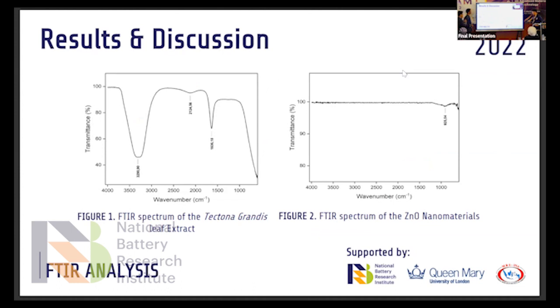Next, result and discussion. Figure 1 shows the FTIR spectrum of Tectona grandis leaf extract. An OH bond in the leaf extract acts as a reducing agent, and formation and stabilization of the nanomaterials was confirmed at peaks at 3290 per centimeter. Figure 2 shows the FTIR spectrum of the nanomaterials. The absence of absorption peaks at wave numbers between 4,000 to 1,000 per centimeter indicates that the resulting ZnO has high purity.